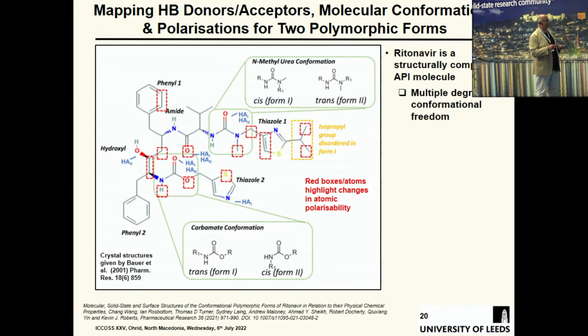It's a bit geeky, but the key thing about the 2 polymorphs, which was pointed out by Bauer, is that a lot of it forms around the conformations around two groups, the N-methylurea and the carbamate conformation. And in form 1, it's cis and trans, and in form 2, it's trans and cis. And the other thing you notice is that when you do a charge calculation, some of the form 1 structure is more polar. We'll come to that later on.